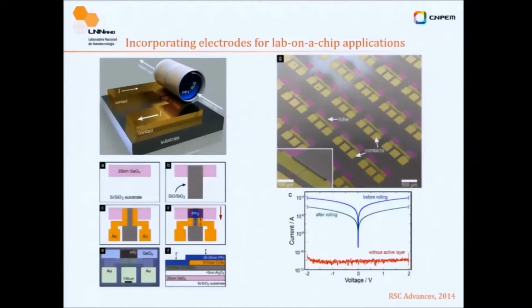The reason is that you have a problem with a CO group that is created every time you charge and discharge the polypyrrole. This is a previous work we did to figure this out. And here, without the active layer, basically there is no current across your system. The trace simply says that we have transport in between the two electrodes and it goes across the polypyrrole.